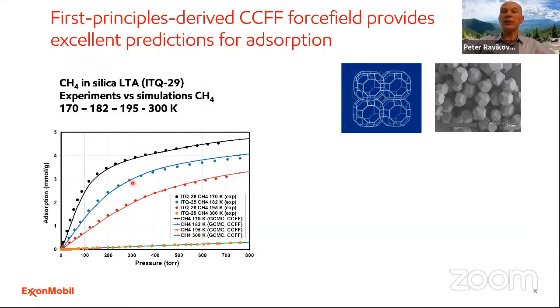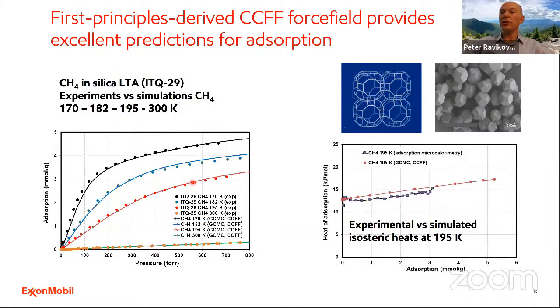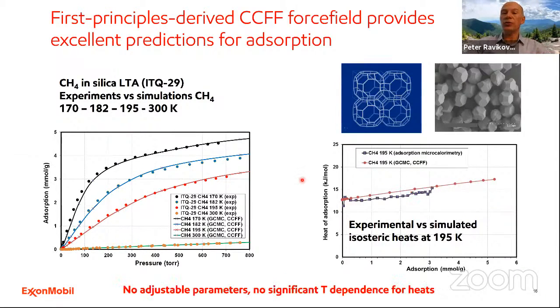This is an example of methane adsorption isotherms at different temperatures in comparison with the experimental measurements. And this is a very good agreement, as well as the agreement for the heats of adsorption, which were measured by calorimetry, and I will be talking more about calorimetry. The point here is that there was no fitting involved in these calculations. So these are predictions.